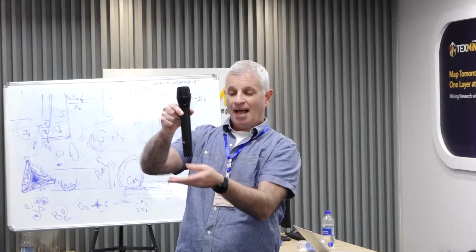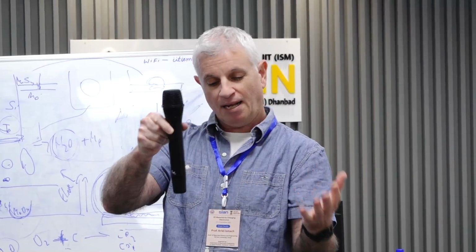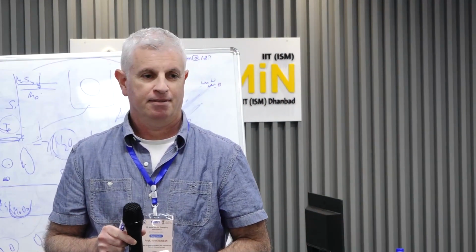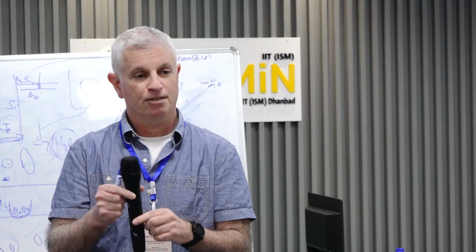You attach it to the melt, and you have a single crystal growth by attachment to the preferred sites. Because of the high temperature melt, there is a lot of diffusion, also a lot of thermal heat dissipation, a lot of processing there. But you don't nucleate anything there. It is already nucleated. You're growing. The seed is basically your nucleus.